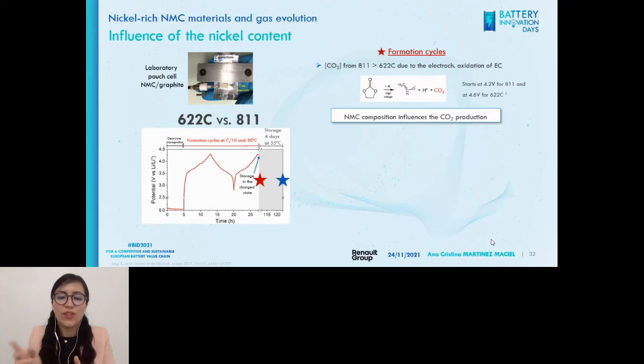Then we also wanted to evaluate the influence of nickel content. So we compared the gas coming after some cycling of 622 or 811 and the gas coming after cycling plus storage. What we saw after the formation cycling steps was that the CO2 coming from 811, from the pouch cells containing 811, was higher than the one coming from 622.